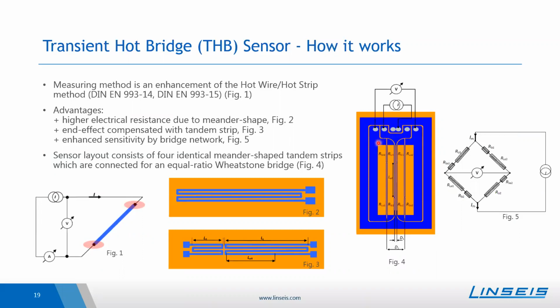So advantages of our THB sensor compared to, for example, the TPS method is that due to this bridge voltage, which is already built into the sensor, we have an enhanced sensitivity and thus an enhanced accuracy. With some other models, like for example, the TPS method, typically the bridge voltage is not within the sensor, but within the instrument. And this is resulting in a lower accuracy and also in a more complex electronics. So the advantage of this bridge voltage here is the enhanced sensitivity.